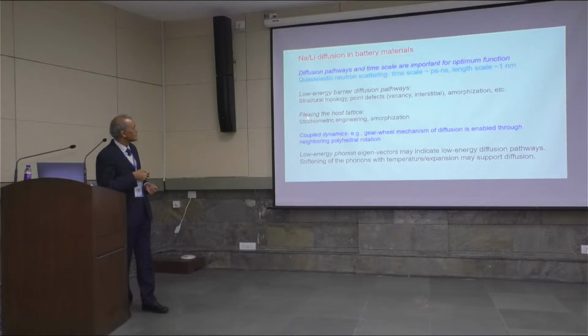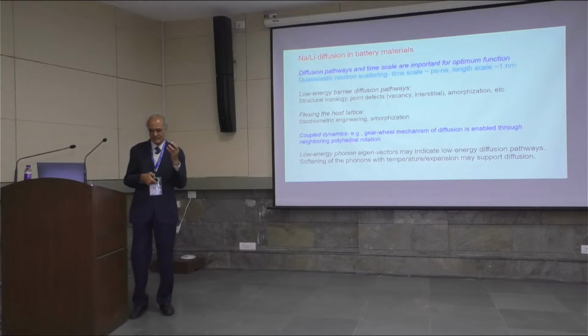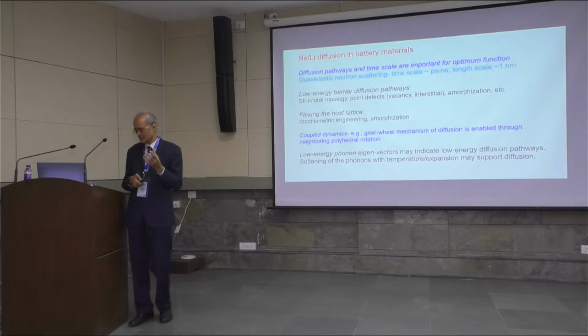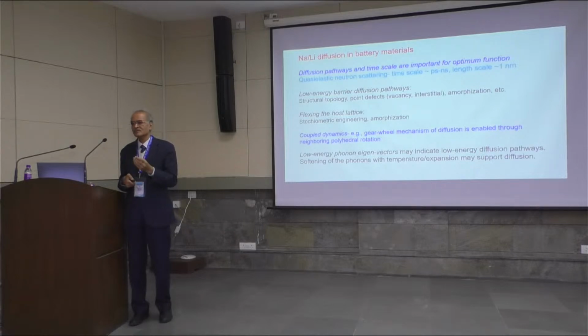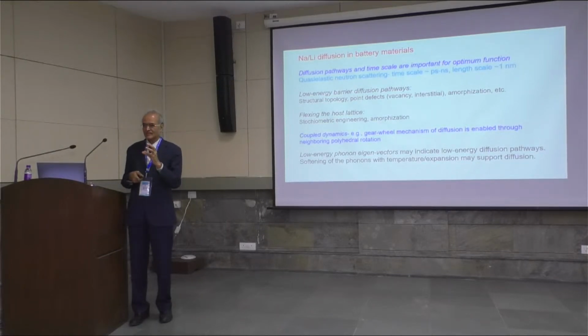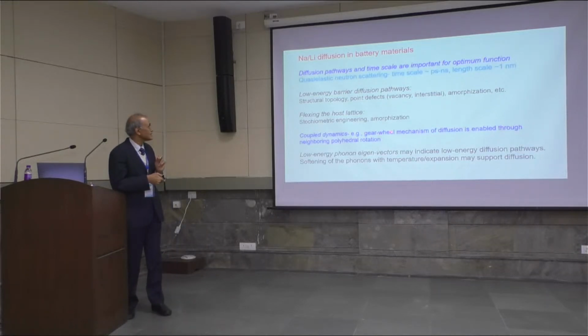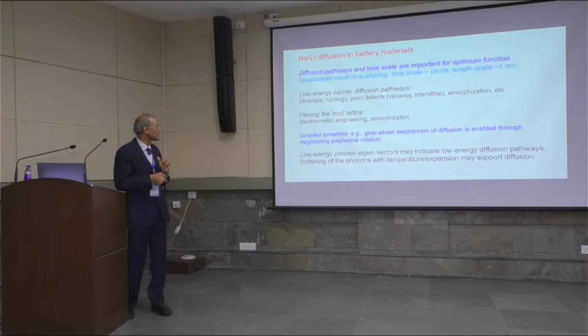Then the other aspect is whether you can flex the host crystalline lattice by some stoichiometric engineering or amorphization methods. Then a couple of things that we found is that in certain materials, if you have polyhedra, some groups like SiO4, so lithium sulfate, for example, or lithium phosphate, a polyhedral group of atoms like PO4 or SO4, its rotation is coupled with the translation of the lithium atom, and that is called a gear wheel mechanism, and that kind of thing helps in diffusion.